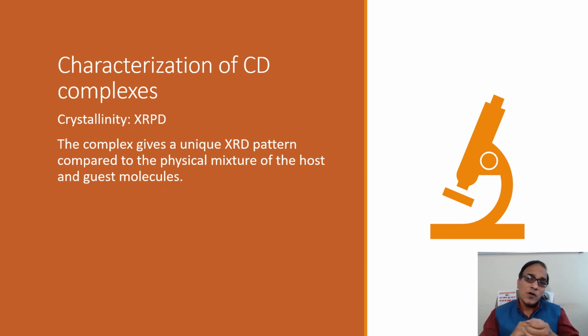Crystallinity is one of the most important parameters because the drug is being converted from crystalline to amorphous. So XRPD can indicate that the complex gives a different X-ray diffraction pattern compared to the physical mixture of the host and guest molecules. So by this we can have an idea. We will be discussing with examples. We are not just limiting to this discussion only.